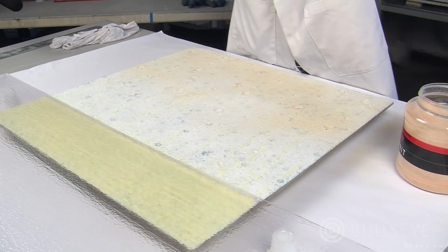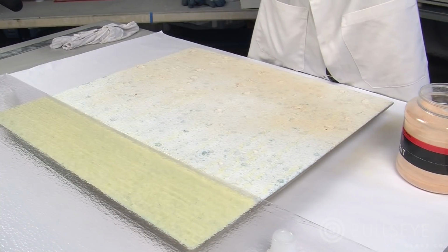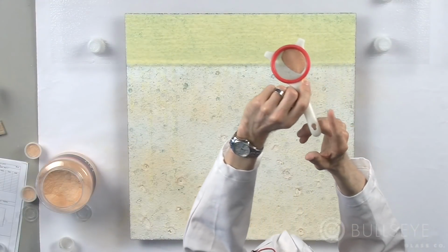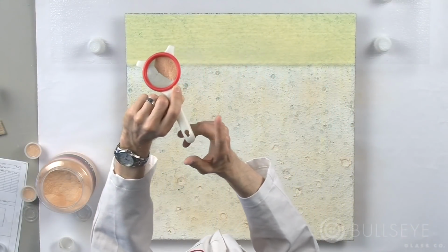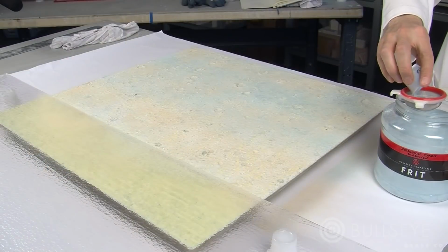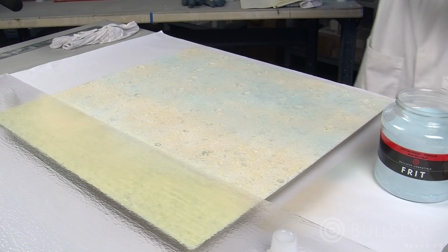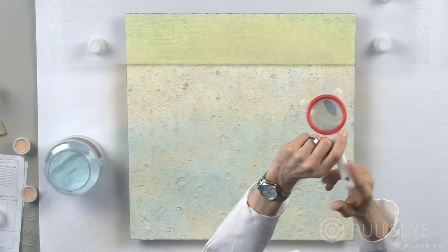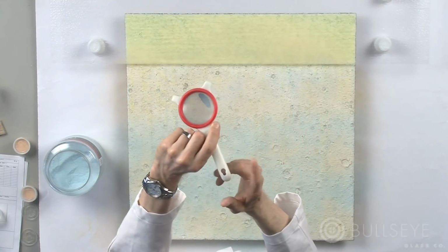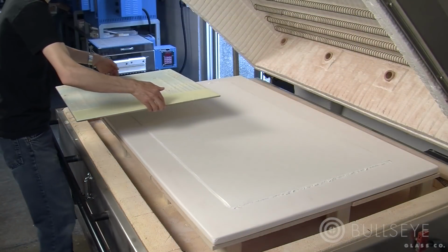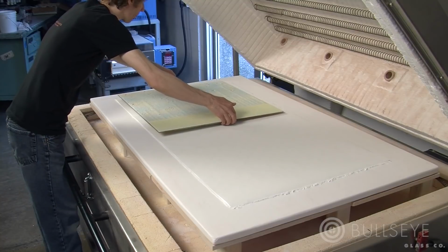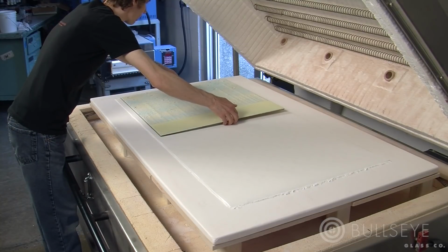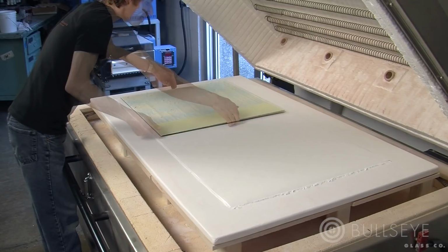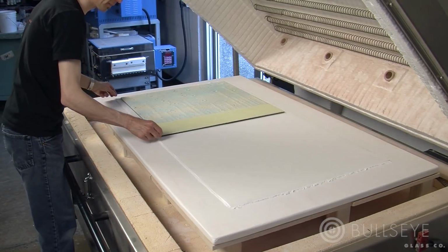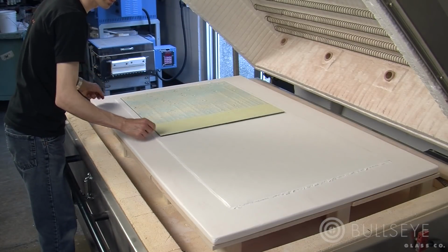Then I'm going over the bottom area again with 1122-08, which is the red powder, about half a cup over the whole thing, just a light dusting, and then I use 0146 over the bottom area for another light dusting. And then I load the piece in, and this is on that fired fiber paper with a fresh piece of thin fire on top of it, and that's important because that will actually emboss the texture that's on the bottom surface and preserve it.